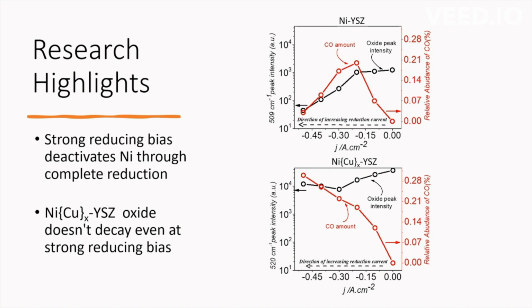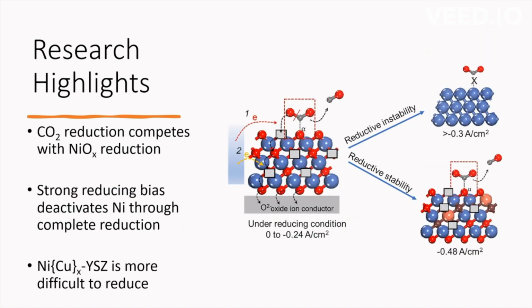Now why is the oxide required to carry out the CO2 electrolysis? When we look into the mechanistic insight, carbonate is the reaction intermediate of CO2 electrolysis. So for formation of the carbonate, there should be a surface oxygen where the CO2 gets absorbed and forms carbonate. In the second step, there is cleavage of the C-O bond and formation of oxygen ion, and to trap this oxygen ion, there should be an oxygen vacancy so that it can be transferred to the anode where it gets oxidized. So in case of nickel and nickel copper, as it maintains this type of defective structure up to a current density of 0.24, it carries out the CO2 electrolysis.